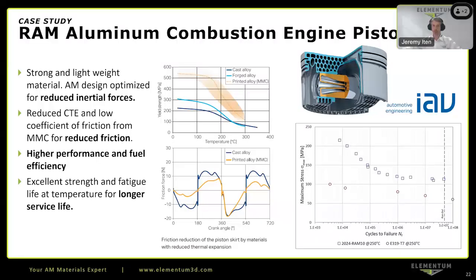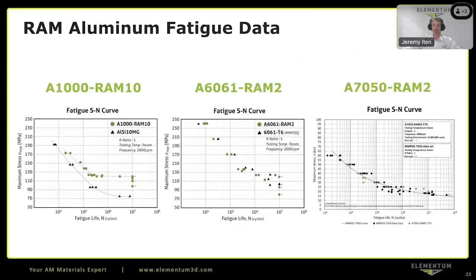And one unique behavior is that you start to see a certain stress threshold with some of the higher RAM fractions, where the material starts to behave more like a BCC type material or like a steel, where you get a fatigue limit, where below that stress your cycles approach almost infinity, where it's really hard to fatigue the material below a certain stress threshold. That's not normally the case for aluminum materials. But with the higher RAM amounts, these composite type materials tend to exhibit that fatigue limit type behavior.